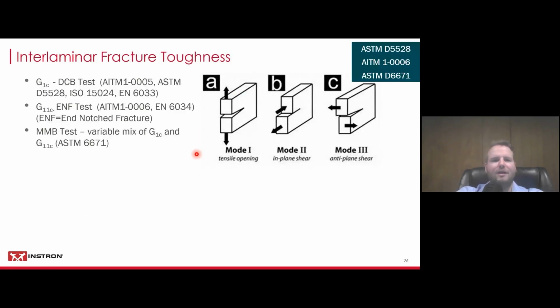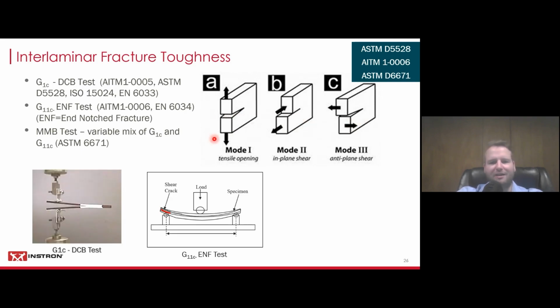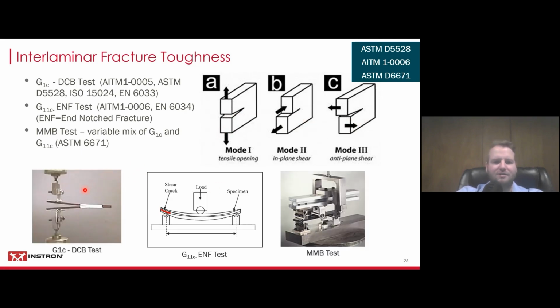Want to look at interlaminar fracture toughness here as well. ASTM D5528 for the mode 1 opening is by far the most common. There's also mode 2 and mode 3, and then there's a mixed mode bending. They kind of look like this. The first one here is the G1C test for the mode 1 tensile opening. So you have a double cantilever beam specimen that you can see here, where you have a crack initiation. You typically kind of force that.